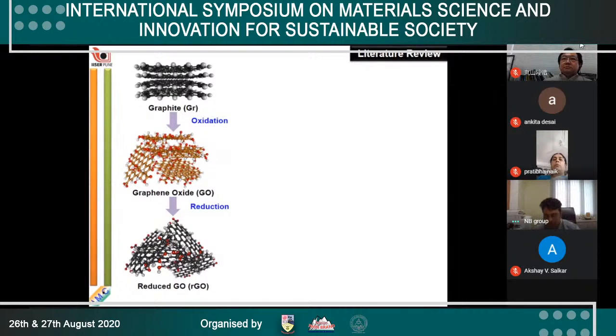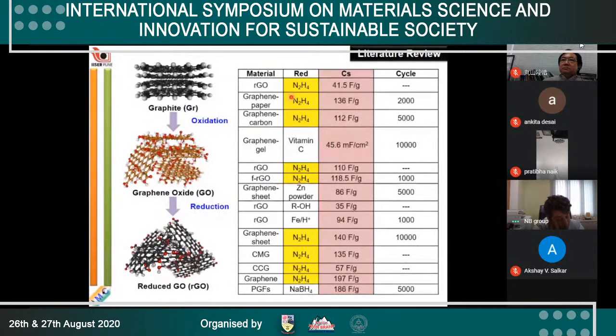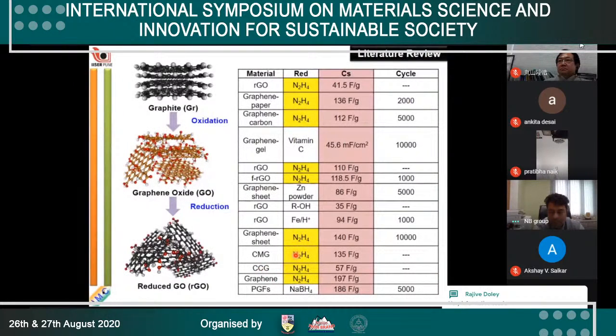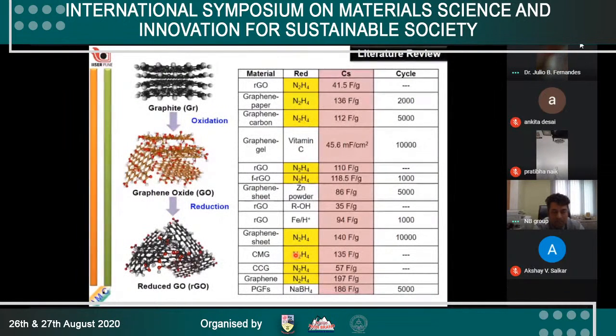One realistic approach for batch-wise production of say 100 gram or 1 kilogram is top-down approach, whereby we need to perform one oxidation and one reduction reaction. Oxidation of graphite to graphene oxide, that we don't need to invent. It's already being done in 1950s by Hummers and Offeman, so-called Hummers method. Little bit of modification one can apply. As for the reduction of graphene oxide to reduced graphene oxide, people are using these reagents. So this is chemical reduction of graphene oxide to reduced graphene oxide. Typically, it is the hydrazine which is being mostly used. In such chemical reduction, average capacitance value of RGO is below 100 farad per gram and stability few thousand cycles.